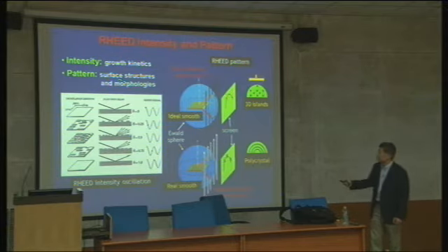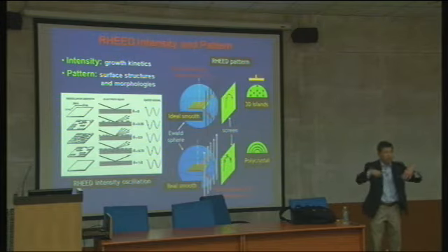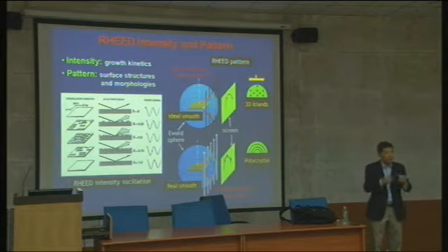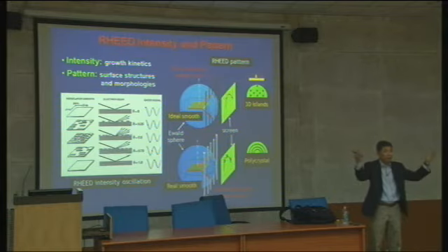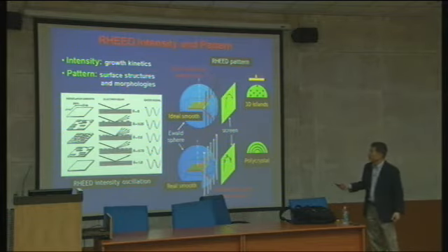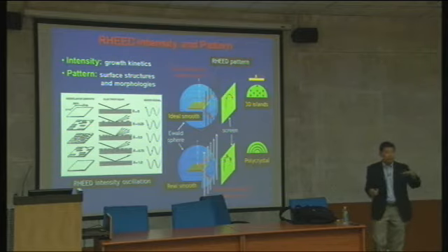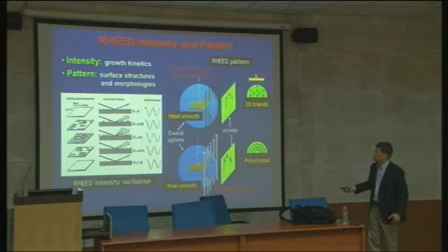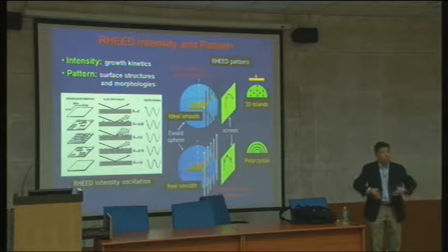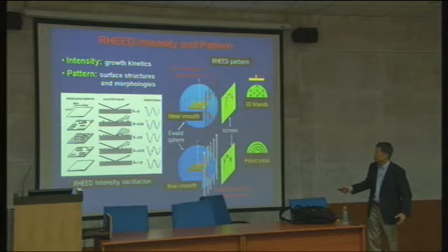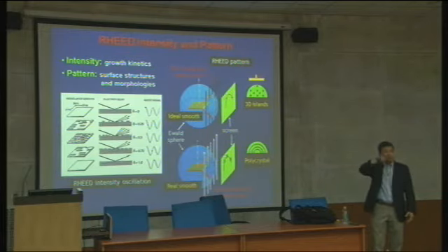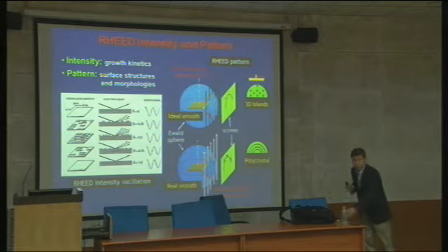Okay? And this bright beam is there initially, and when atoms arrive on the surface, it's like a water droplet on a mirror, the reflection is scattered everywhere and the intensity goes down. This intensity goes down to a minimum at roughly 50% coverage. Then when you go to full coverage, you go back up again. So one single oscillation corresponds to one monolayer.